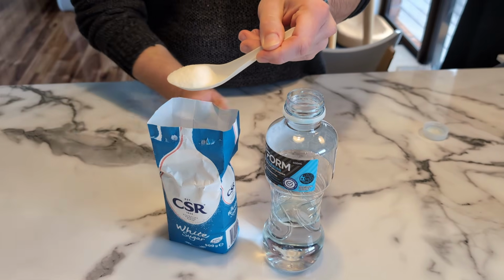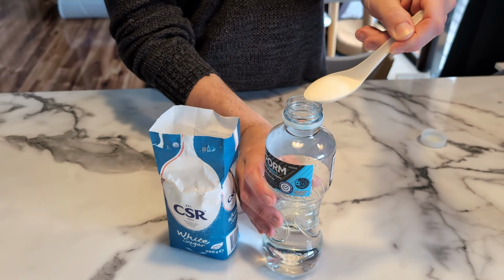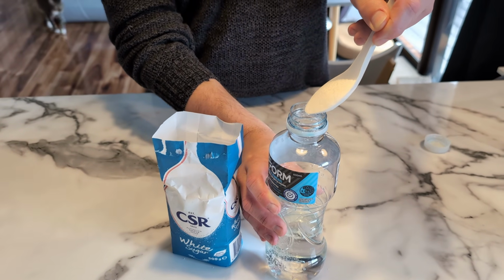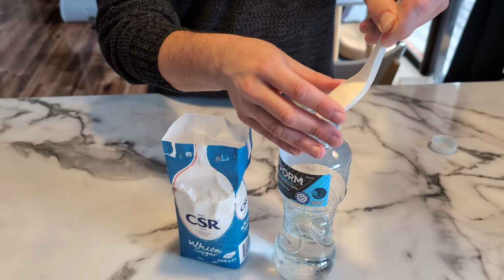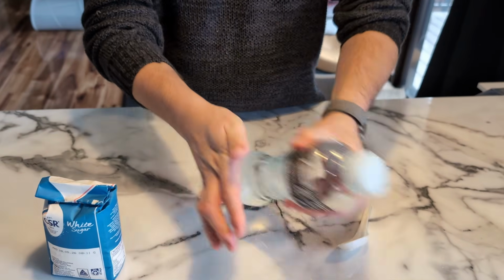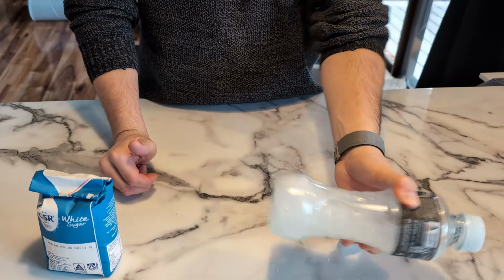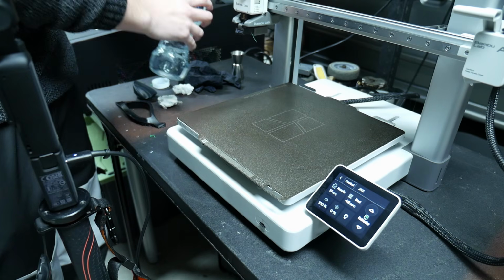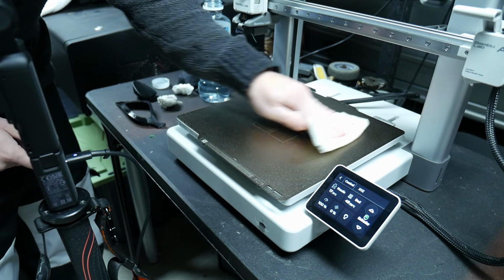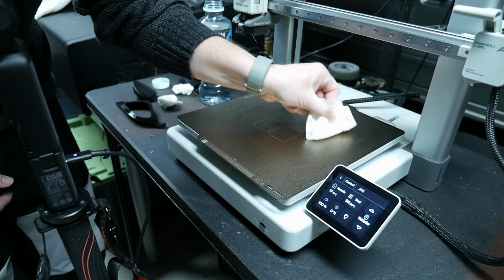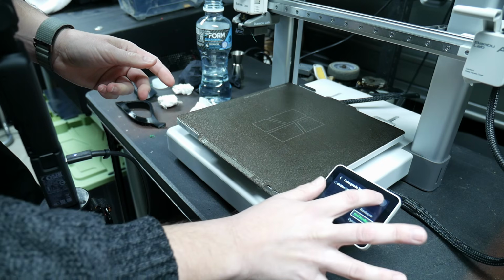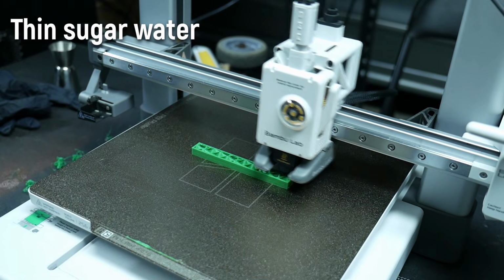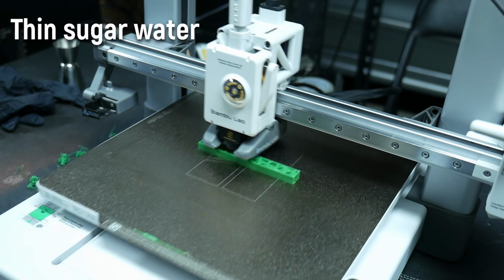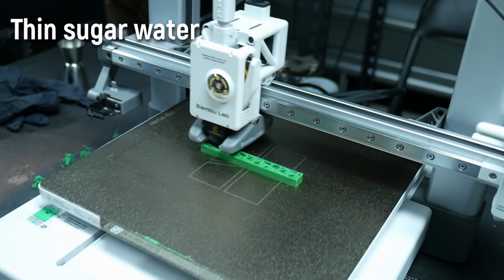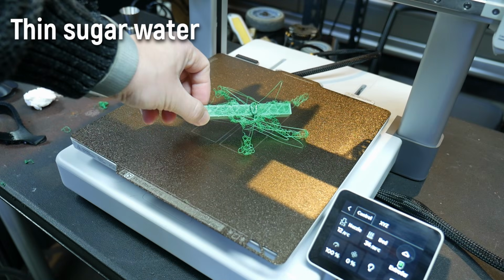I wasn't sure how much sugar to dissolve into the water, so I started with roughly 2 tablespoons into around 100 milliliters of water, using a sports drink bottle to shake it up and dissolve it all, which I thought was quite fitting. I then applied this liquid to the heated print bed to speed up the water evaporating and spread it around, repeating a couple of times until I was left with a slightly sticky surface. It really does feel sticky, so I was quite hopeful, and the print started out great, but just like before,